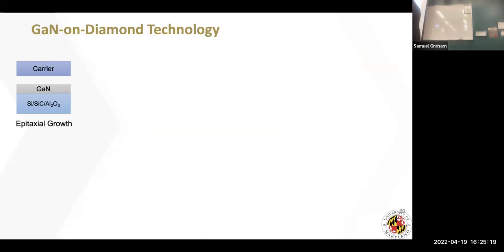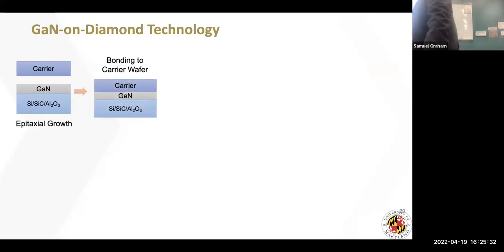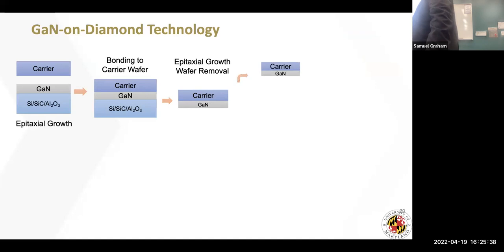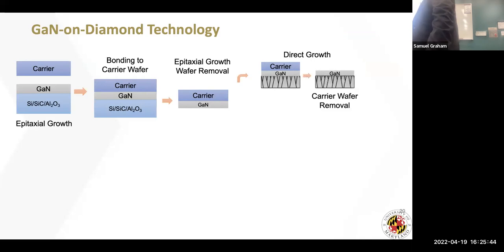So you start out with gallium nitride grown on your favorite substrate. It could be sapphire, silicon carbide, or silicon. A lot of people use silicon. I will take a carrier wafer, I will bond it. And so when I do that bond, then I can remove that bottom substrate. So now it's just sort of stuck to this carrier wafer. I can take that carrier wafer now and I can grow diamond on the back. So this is called direct growth. We've done a lot of that. That's what the previous study that I just showed you, that's how it's done. And then I remove the carrier wafer.